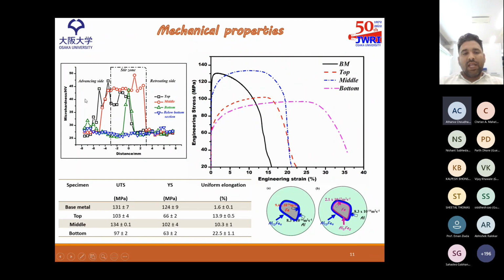And also in the stir zone, since the particle dispersion is homogeneous as we have seen, the higher and homogeneous hardness is obtained. Whereas in the advancing side, the top section, the particles are dominant on the advancing side. That's why the higher hardness on the advancing side is obtained.